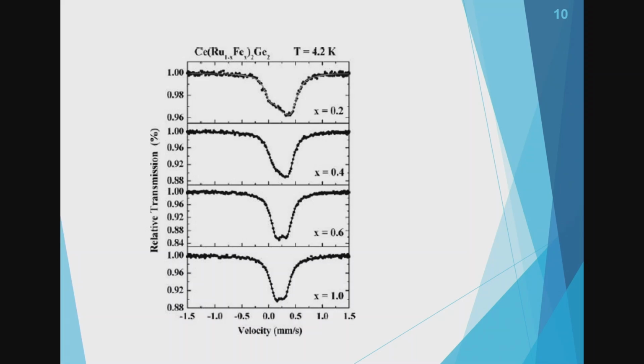So Elisa was very important in this work, of course, because she interpreted this as a B hyperfine field transferred from the cerium ions, because cerium is 4f, so cerium has a magnetic moment. So the B hyperfine field that you see here is transferred from the cerium moment, and it has the same order of magnitude as the quadrupolar moment. And though we had this idea that we had to use B hyperfine and quadrupole with the same order of magnitude, we could not come to a conclusion by this first experiment we did.